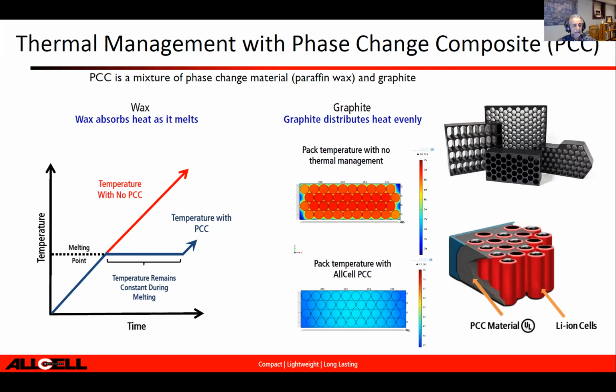the heat, as you see in the graph to the left, when you heat a battery or any system that has sensible heat only, the temperature continues to increase until you have to stop it. For example, in batteries, when the battery temperature exceeds certain limits, 60 or 70 Celsius, you get into the unsafe zone, and therefore you start throttling down or stop the vehicle from operating. When you have a phase change composite or a phase change material similar to the one we have here, once you hit the melting temperature, the material starts to transition from solid to liquid and absorbs a significant amount of heat in the form of latent heat.